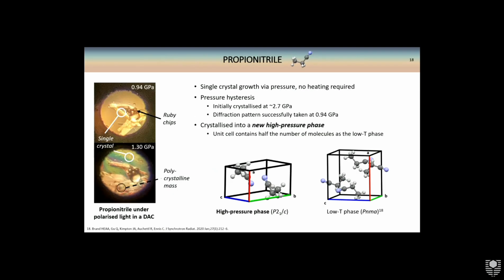And so we were able to successfully form and characterize a single crystal of both propionitrile and butanenitrile. First off, with the propionitrile, we've managed to develop a way of growing these without needing to heat up the diamond anvil cell, which is what you normally have to do to get a single crystal. We found that upon increasing the pressure, it initially crystallized out at 2.7 gigapascals, but there was a large pressure hysteresis where it remained crystalline all the way down to about 0.94.